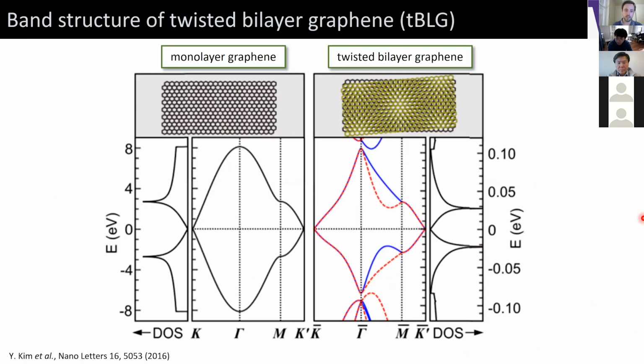Now, if I stack two metals on top of one another, like two layers of graphene, for instance, then their band structures can be highly modified. They can hybridize strongly and can change substantially as a consequence of this Moiré pattern. So if I look at the band structure of monolayer graphene, we know that at low energy at the K and K prime values, we have this linear dispersion. And then at higher energy, there's a Van Hove singularity, and then the mass of the band inverts.